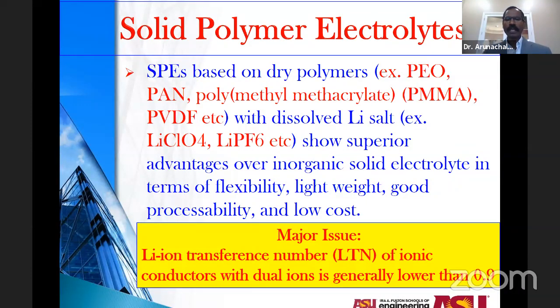But because these solid polymer electrolytes also have a cationic lithium and also an anionic component, that actually leads to a relatively lower lithium ion transference number. Most of the literature talks about less than 0.7. One of the reasons, one says they could actually increase the transference number of lithium ion all the way up to 90%, but still, it's not 100% ionically conducting. So that's one of the major disadvantages with the solid polymer electrolytes.